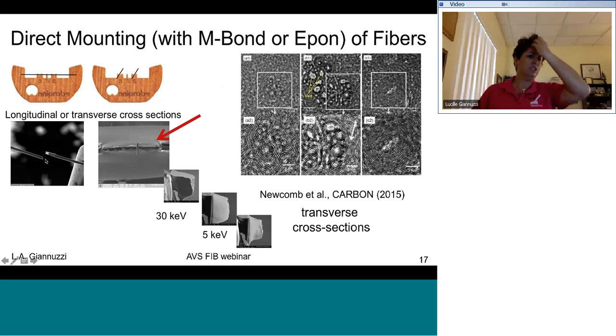Okay, and this is really important because once the sample starts to get really thin with the FIB, you don't want to put any stress on this. So you can see here that in cutting the sample free, the stress release actually caused the ends to move several microns. And so if the final thin sample was just holding this together, that would put a lot of stress onto the thin sample and probably break the sample.